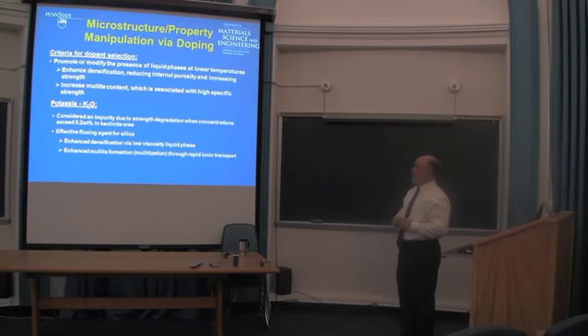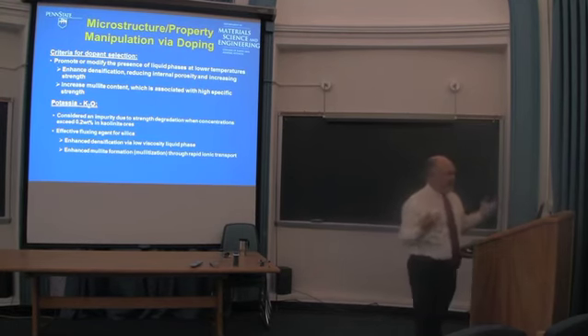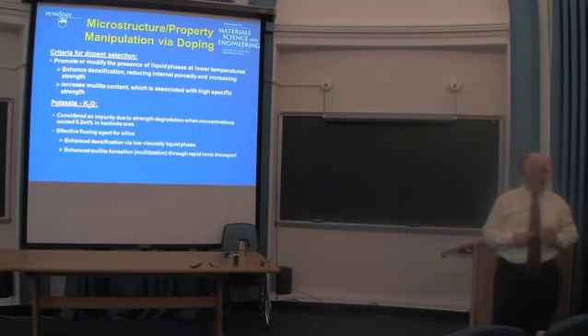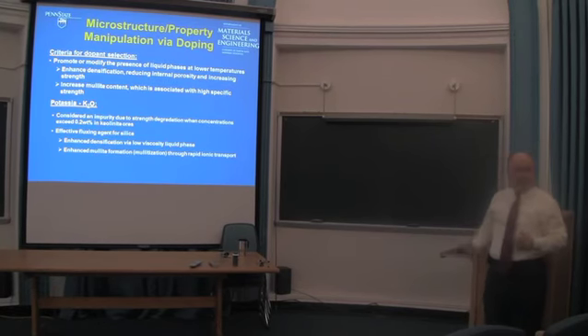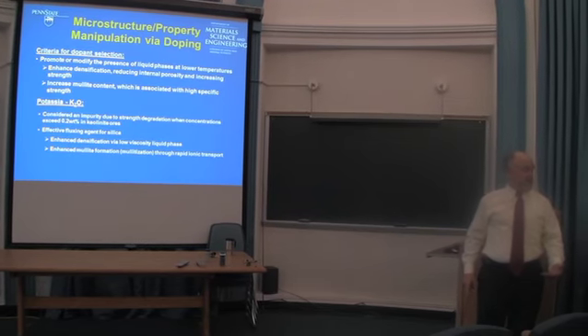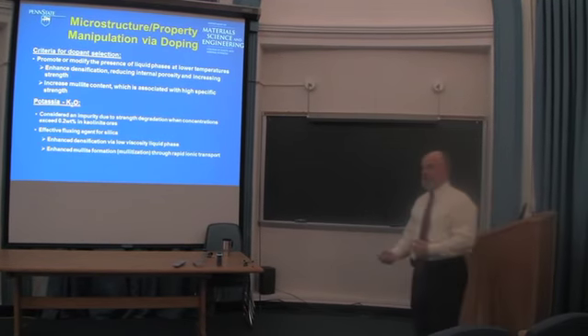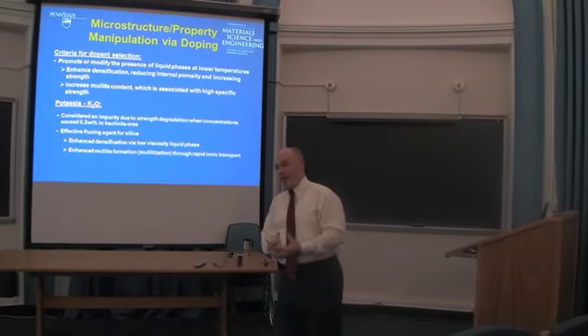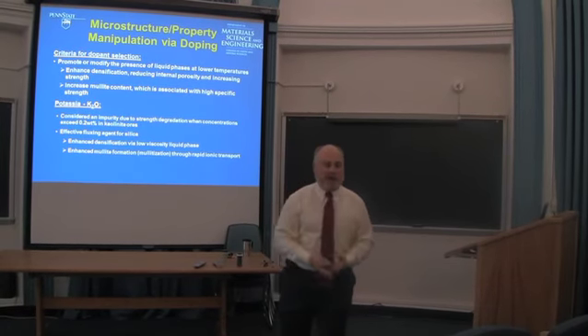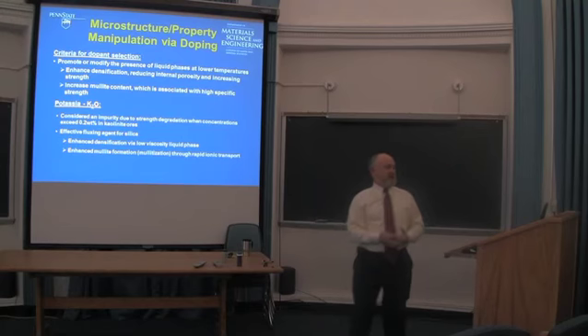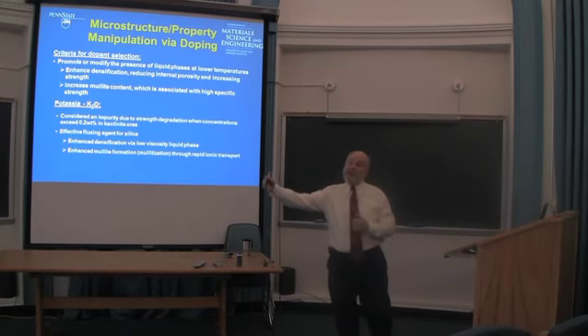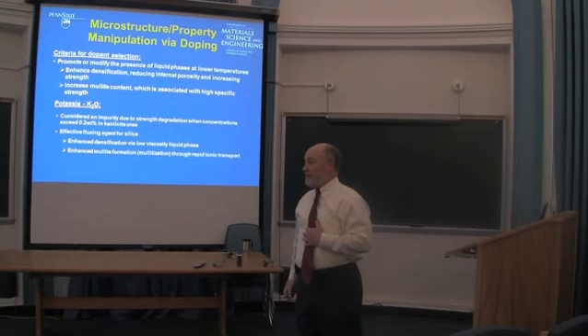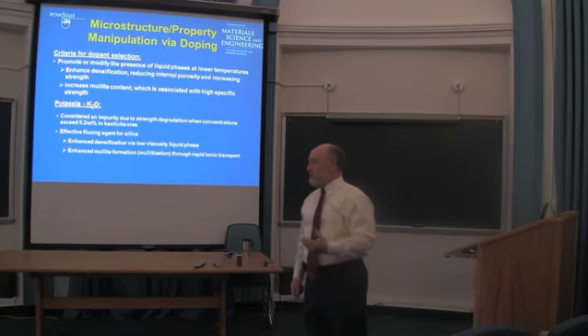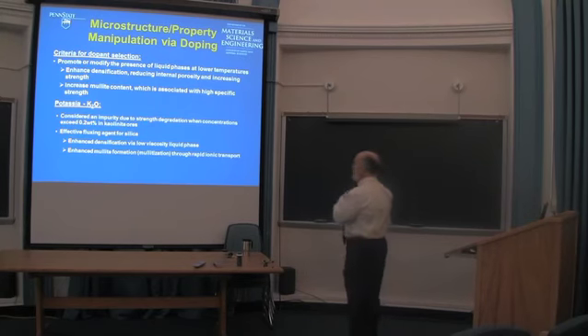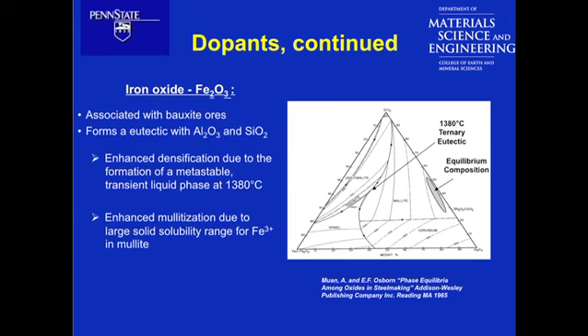Potassium was one of our dopants because it's an alkali oxide. Basically, what it does is it lowers the viscosity of the glass phase during sintering. So my solution precipitation processes and my particle rearrangement happen fast. I can sinter faster, and I can suppress the evolution of certain phases that happen at the latter ends of your sintering run. Okay? This is what we do as ceramists. Right. We also looked at iron oxide. I think that's on the next slide.